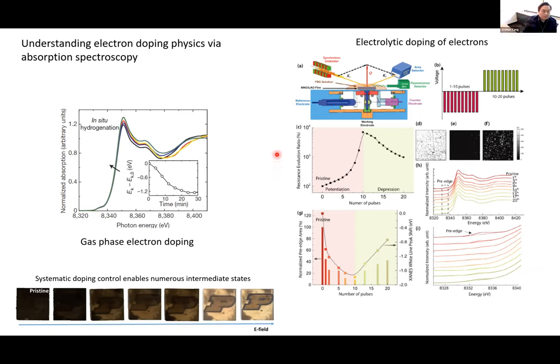Okay, so you need to protect it very well if you deal with the proton, right? Otherwise, you expose it to air, you have water. We have done a lot of our work on exposed surfaces, in part because we also tried to do spectroscopy on the same samples. We find that having the exposed surface is very useful. These samples are exceptionally stable at room temperature for months, sometimes even over a year, because we have to wait for beam time and things like that. So at room temperature, even a fully exposed sample, there is no problem. But if you want to heat it up, then it helps to have a silicon dioxide passivation layer on top.